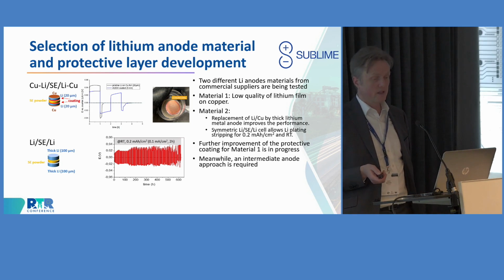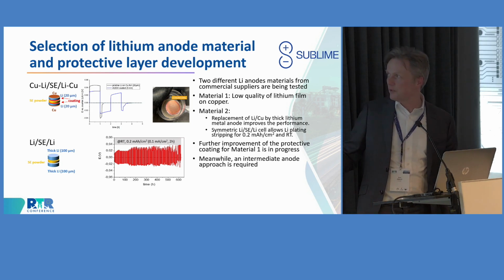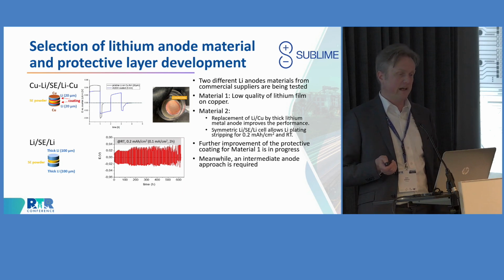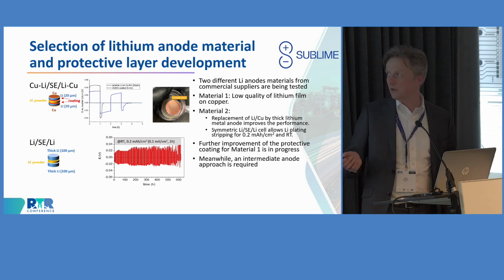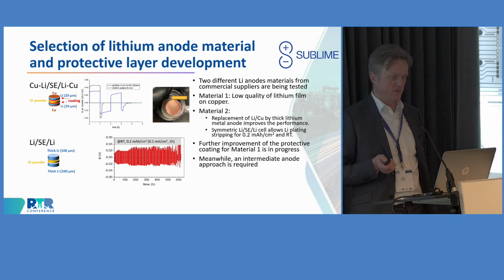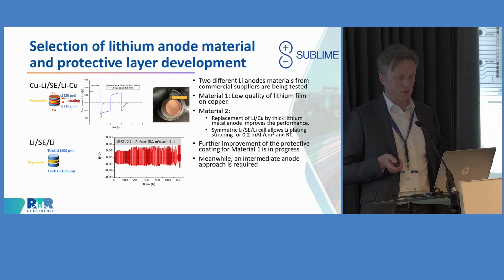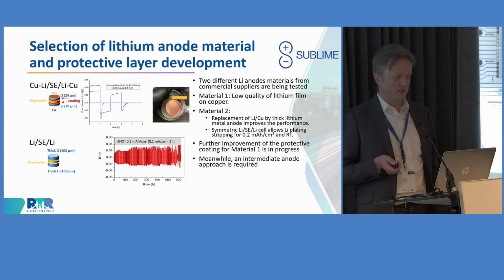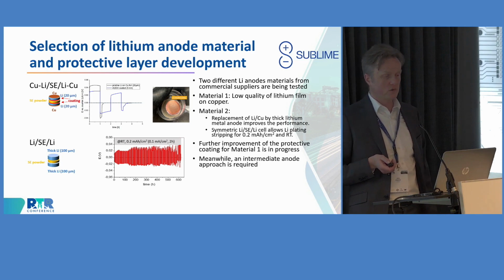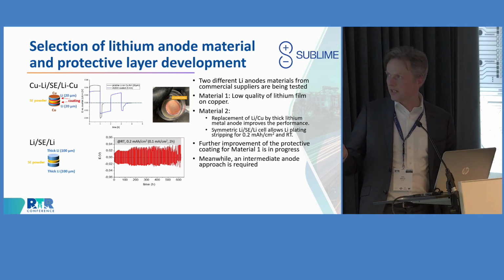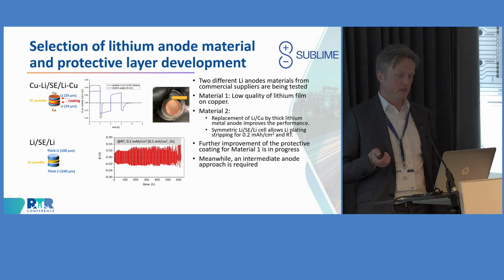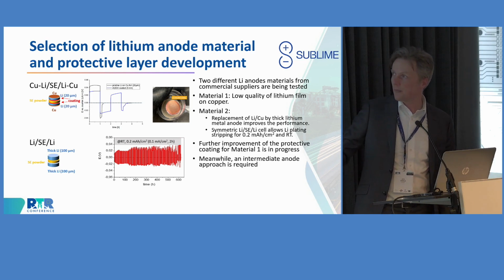For example, the first material, which in principle we need in order to really reach the very high energy densities that we are targeting, that's very thin lithium on copper. That seems to be kind of low quality at the moment. So cycling of these things, especially also with the development and the purification of the protective layers, showed us that we, at the moment, are not yet able with that material to cycle as many times as we like. You see here these diagrams of charge and discharge, and you see this is then at the end